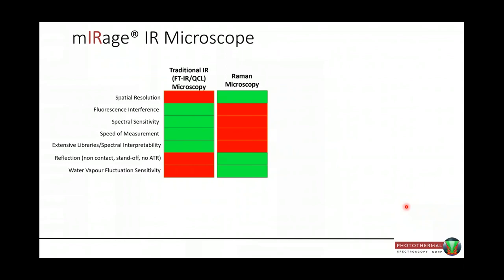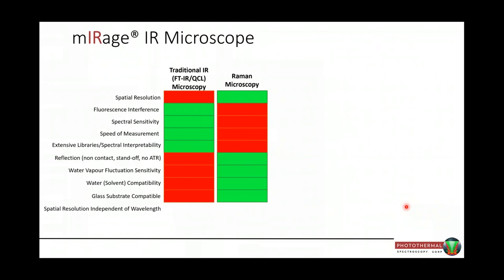Traditional FTIR is very sensitive to water vapor fluctuation, whereas Raman isn't. You have problems with water solvents, aqueous solvents with infrared, which you don't with Raman. You can't work with glass substrates in infrared, but you can with Raman. And the spatial resolution is independent of wavelength for Raman, but not infrared.